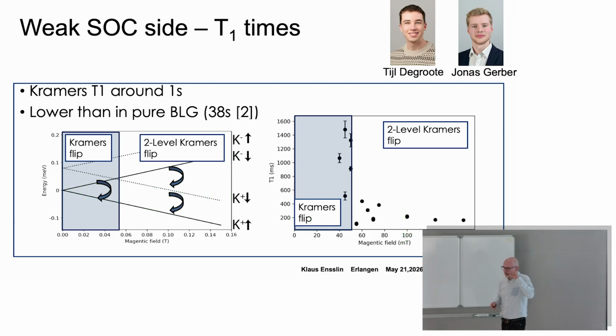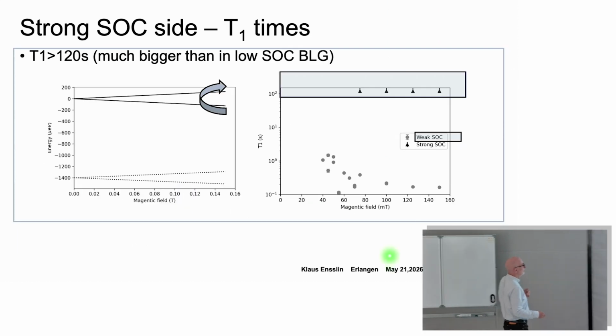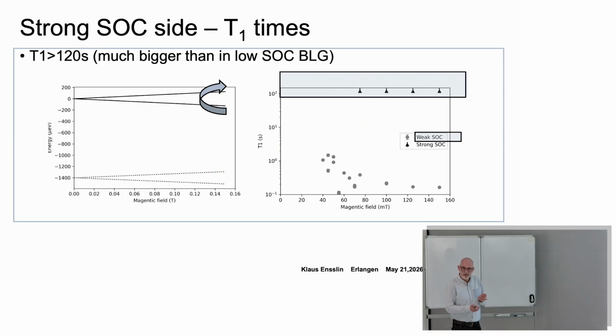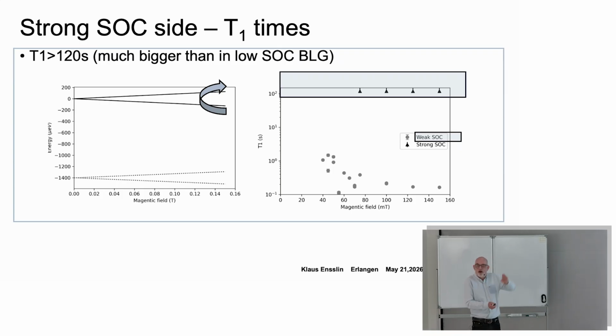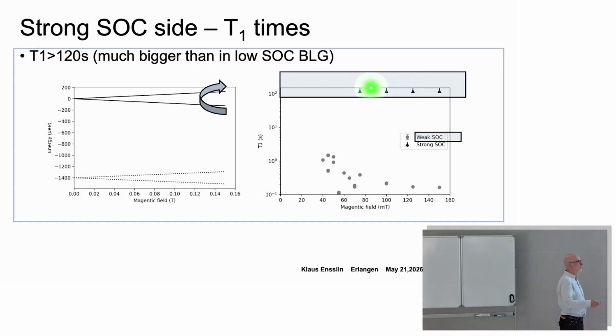Now we take a sample that has transition metal dichalcogenide on top. You see we have this huge spin-orbit induced gap, and you see what we find. We find lifetimes that are so long that we can't measure them anymore. And the reason for that is because you have put all the excited states so far away. Decaying from one state to another state always involves virtual transitions to higher states. If the higher states are far away, then they don't give rise to this decay anymore.